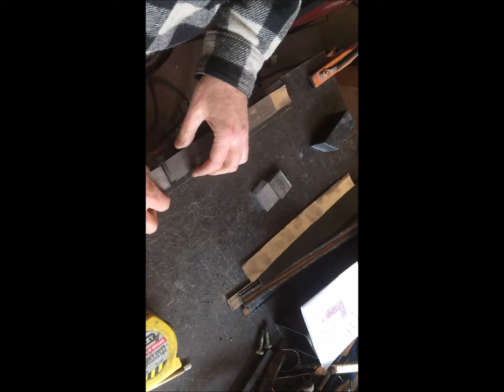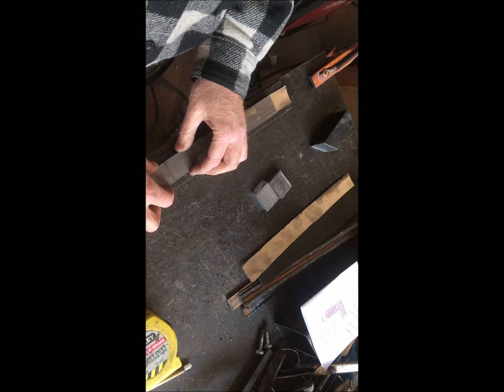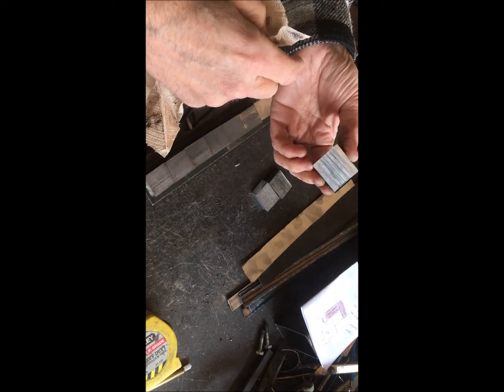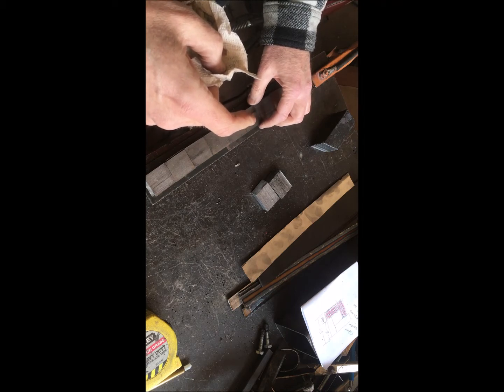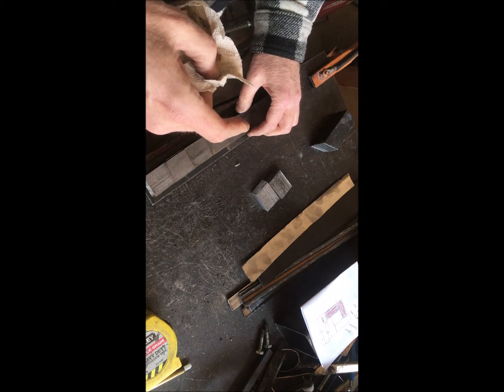Little known fact, you can weld steel at room temperature if the faces are clean enough. If you take two pieces of mild steel this size and machine them off to a 1/10,000th of an inch either side, and then polish them, mirror polish, degrease them, put them one on top of the other on an anvil, hit them with an 8-pound sledge really hard, they will actually weld. I mean, you will never get them apart without a hacksaw, because the steel will actually cohere.